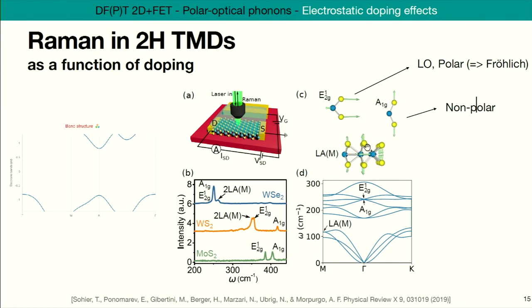So they have this very nice experiment where they gate or they dope the TMD using an ionic liquid gate. And this has the advantage of, one, being able to dope the material a lot, so put a lot of electrons or holes in the system. And it's kind of transparent. So you can put a laser on top, send some photons in there, and see what happens in matter, and do the usual Raman spectroscopy thing. That's actually a way to probe phonons.